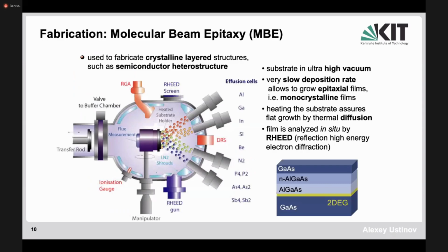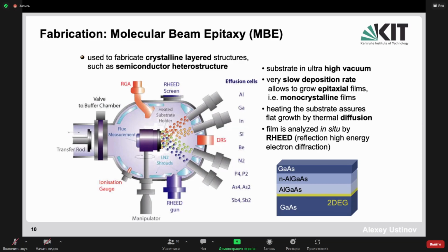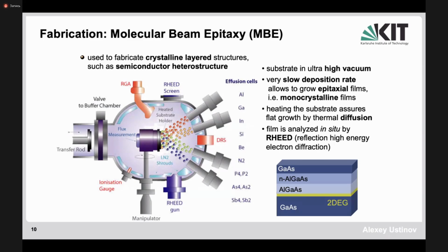The fabrication of these heterostructures involves molecular beam epitaxy, where one can actually, in very high vacuum, grow the crystalline perfect structure on the substrate, making atomic layer by layer deposition. And this requires very high vacuum, as I said, and a very slow deposition rate. It requires also appropriate substrates to grow monocrystalline films. Now, this has to be done at high temperature because the high energy components which come from the effusion cells on the right come with a particular disorder, and then the self-annealing is achieved by growing the structure at high temperature.